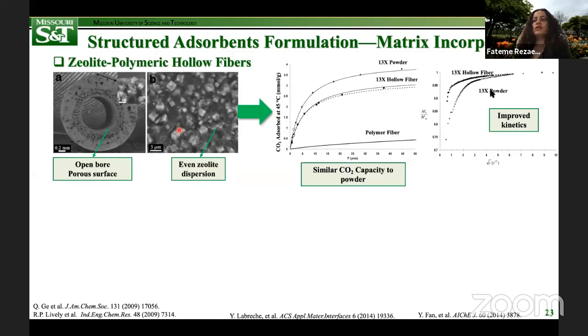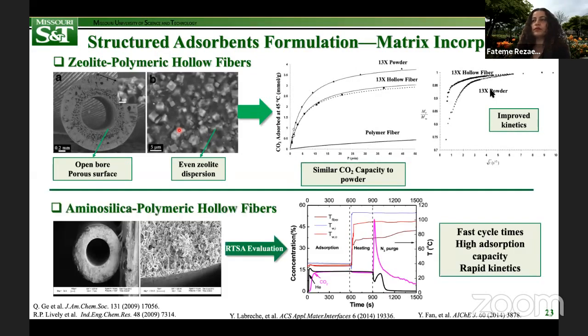Several examples are zeolites incorporated into a polymeric hollow fiber, mainly cellulose acetate polymeric hollow fiber, and their performance in CO2 capture. The hollow fibers' open geometry and high surface area to volume ratio usually allow the CO2 to rapidly saturate within the fiber and therefore give rise to a steeper front, indicating that incorporating zeolites within polymer hollow fibers can be used to manufacture relatively high capacity adsorbents.